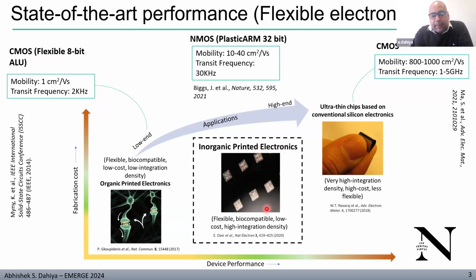Then we have another form of electronics, inorganic material based, where we are using metal oxide or other inorganic materials, and we use printing technologies or conventional fabrication as well, and we can reach a mobility of up to 10 to 40 centimeter square per volt second and a transit frequency of around 30 kilohertz.